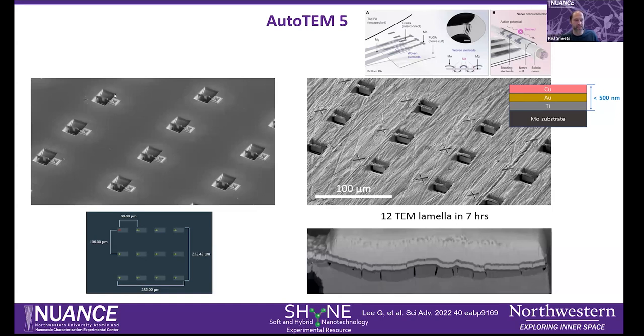So basically it's an optimized recipe for one area, and if you copy and paste that recipe multiple times, then you can just let it run in the software, and after ideally a couple of hours you come back, do something in the meantime, and at the end you would have an amount of samples, in this case maybe 12, that would be automatically prepared.